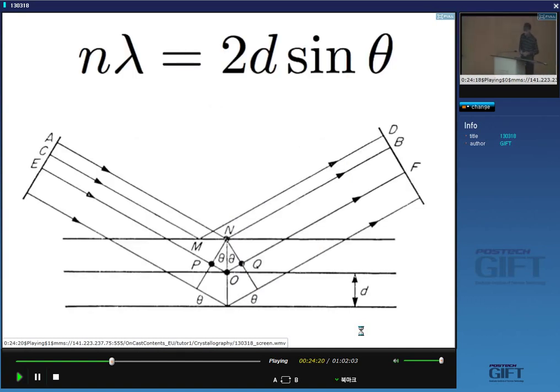Okay, I'm going to derive for you the Bragg law in a very simple way. Okay, the Bragg equation everybody is familiar with, that 2d sine theta equals n lambda gives you diffracted intensity. But if you deviate from the Bragg angle, then you get zero intensity. And I want you to understand why that law works. So imagine that we've got a set of planes here, and the spacing of those planes is d. And you've got your X-ray or electrons or whatever coming in at a particular angle theta.